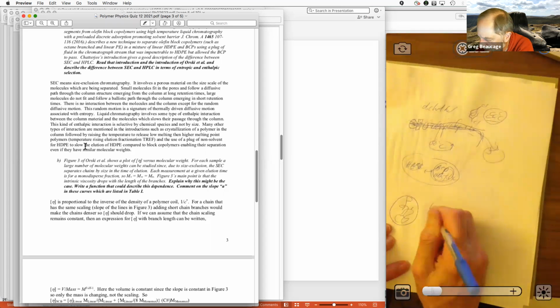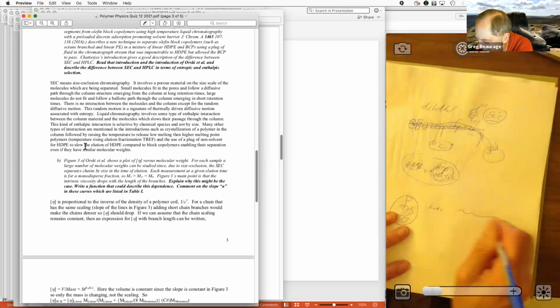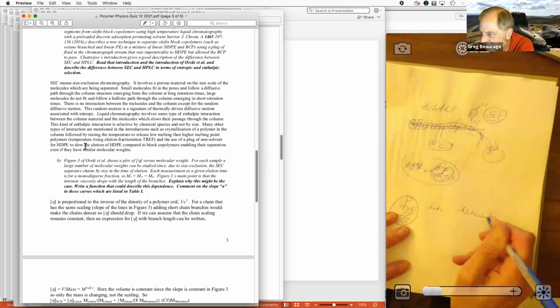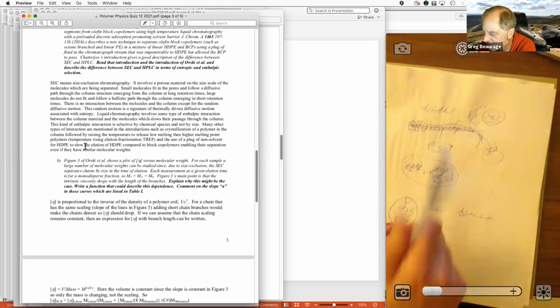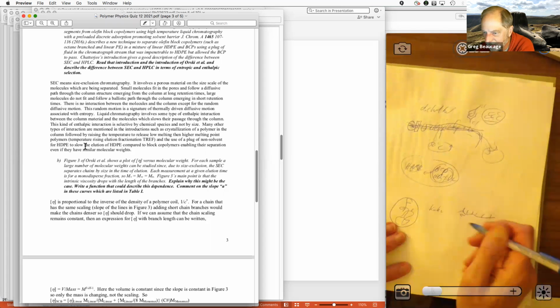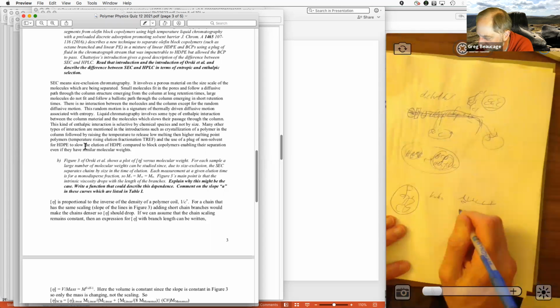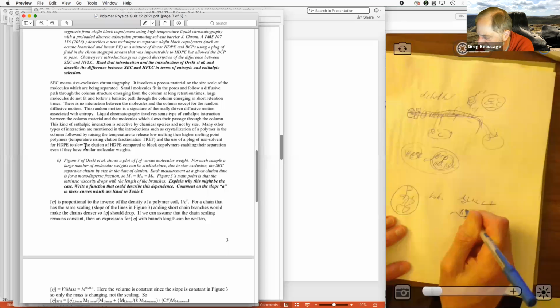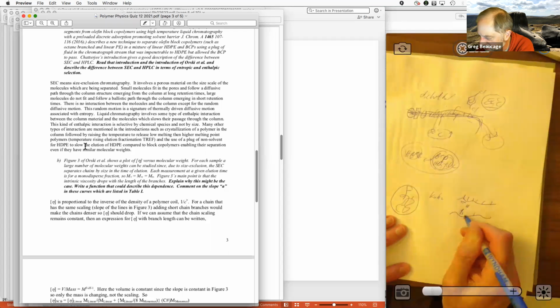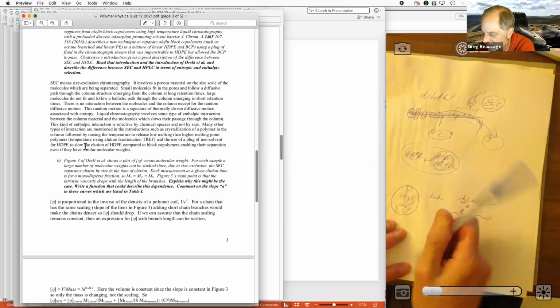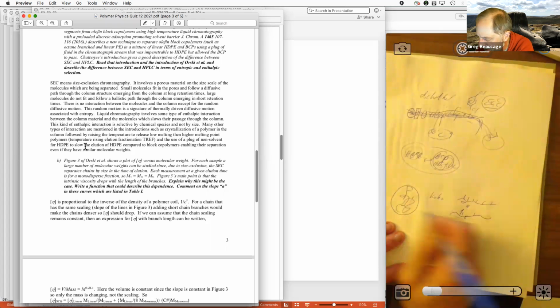We saw that if you had brush polymers, the Kuhn length goes up, but those are spaced pretty close, right? Those are small spacing. But here you have a pretty long spacing between the branches. It's 8 carbons between them, and these branches are like 1 to 10. So apparently it's not enough to change the Kuhn length, so the hydrodynamic radius doesn't change. All it changes is the mass. So your hydrodynamic volume is the same, right? And all you're changing is the mass.